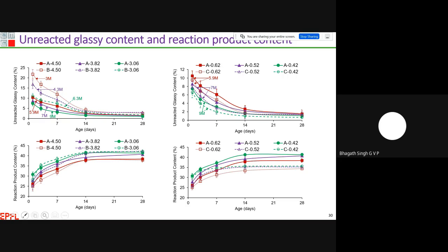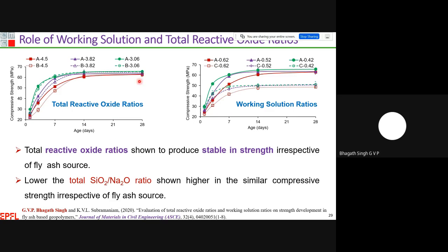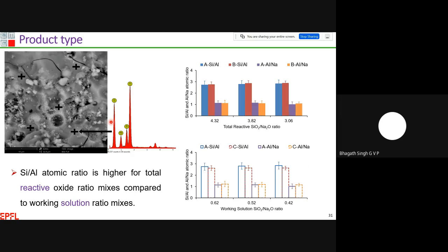And if you compare the reaction product content, irrespective of fly ash, in various mix proportions, both fly ashes show more or less similar reaction product content, which replicates the compressive strength development in the previous slides. And coming to the product type, which type of product is formed in the total reactive oxide silica to sodium ratio mixes as well as the working solution silica to sodium ratio mixes. This is the SEM image at 10 micron scale of an alkali activated mix at total silica to sodium ratio equal to 3.06.